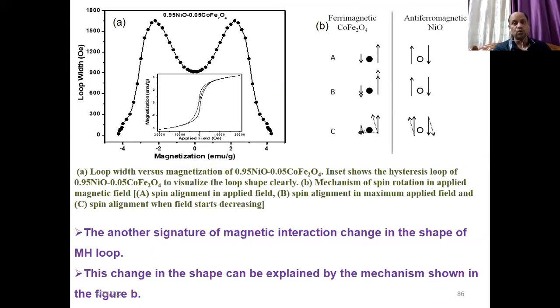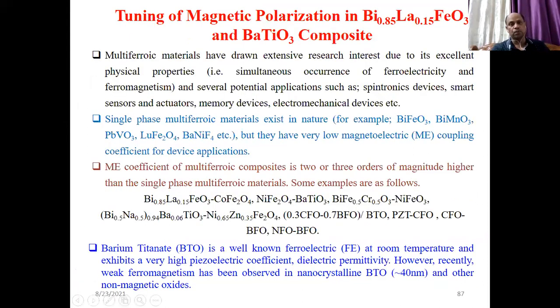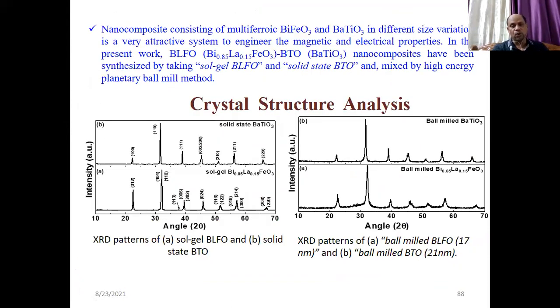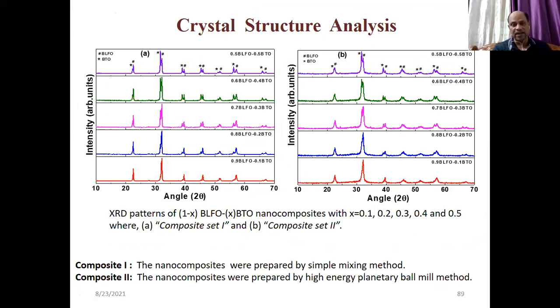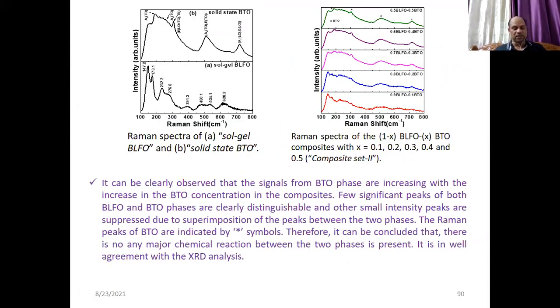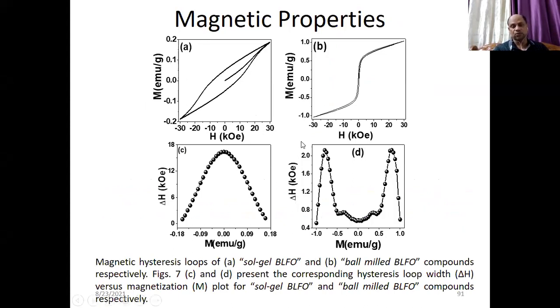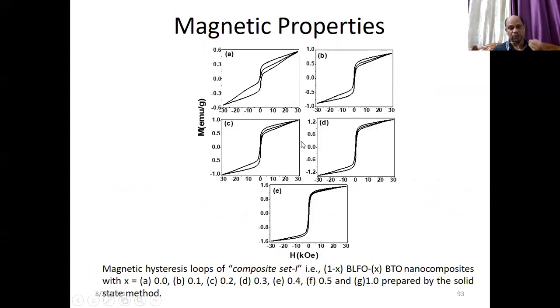The interaction can also be easily seen between them, that they are interacting with each other, and the squeezing of their hysteresis loop. So if you look at BTO and bismuth ferrite, at a very low magnetic field, here we did the extension where we physically mixed, and also ball milled, and also solid state method. With all the methods, it was found that only when you ball mill do you find the interaction between the materials. That also demonstrated that BFO and your BTO interact with each other and show very interesting magnetic properties, which may be better for your multiferroic properties also.